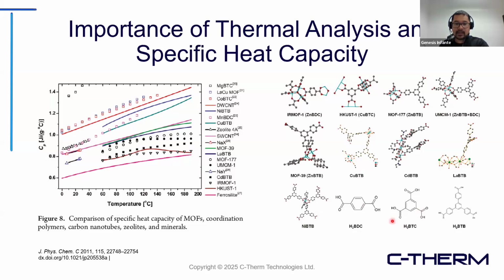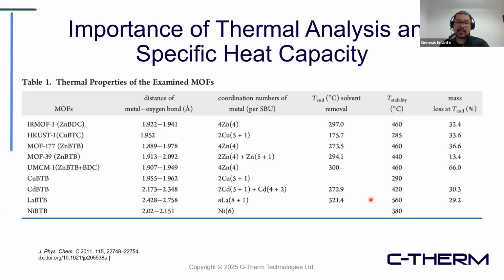So in this paper, what they've done is look into very specific MOFs, and they're trying to understand what dictates the thermal stability of the MOF in general, right? So we're looking at the thermal analysis now, and what they've seen is that there is a portion where you have a mass loss because of essentially removal of the solvent. There are different MOFs here. And at the end of the day, you can see this T stability temperature here. It's essentially the maximum temperature where the MOF became stable after removal of the solvent.